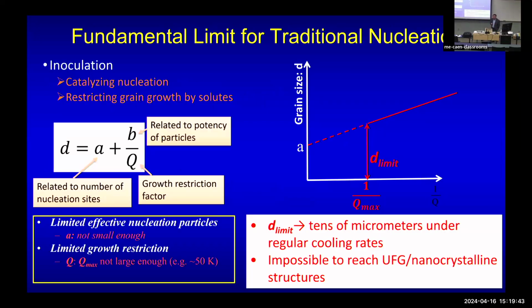We can also see why at that time we couldn't break the traditional barrier. Without self-dispersing nanoparticles, the fundamental limit for grain size during casting is governed by this equation. The grain size depends on how many nucleants you can have, how effective the nucleants are, and especially this one, growth restriction. Traditional nucleant theory is dependent on chemistry, right? When you push that solute out, it is enriched at the front and blocks growth, but there is a limit. Normally Q is about 50 K, mostly in the industry. That's why we didn't get this one, we get larger grain size, right?